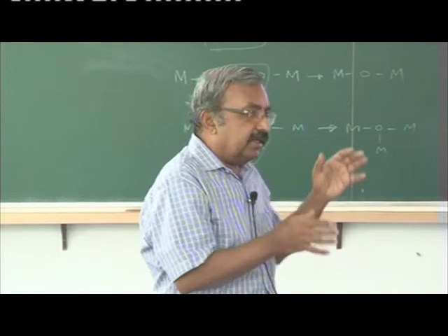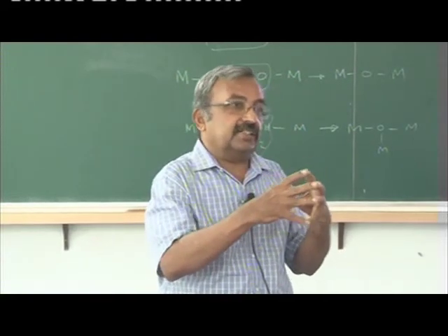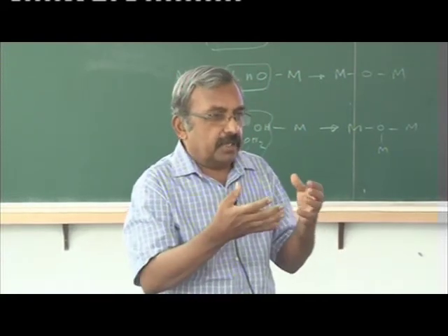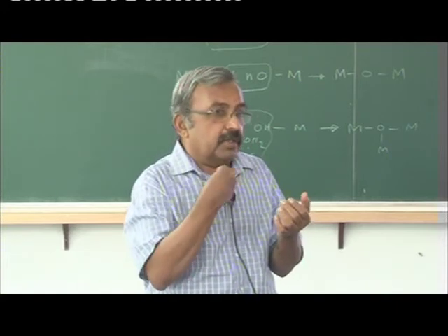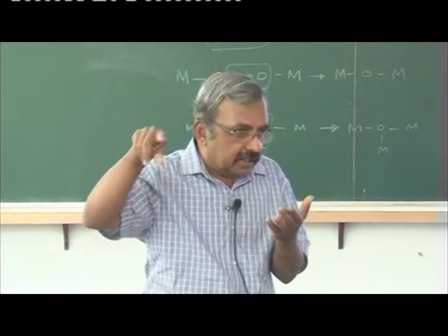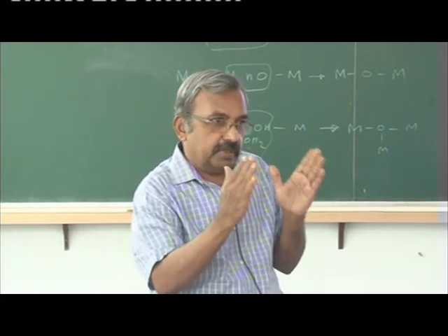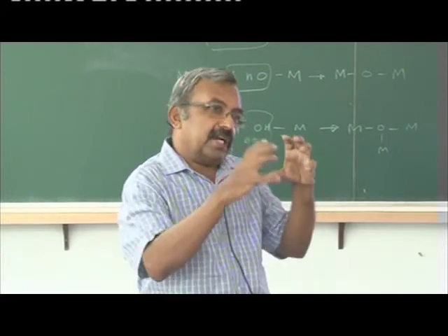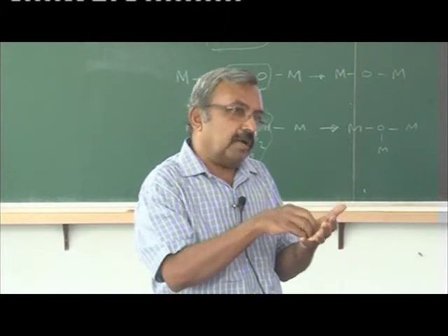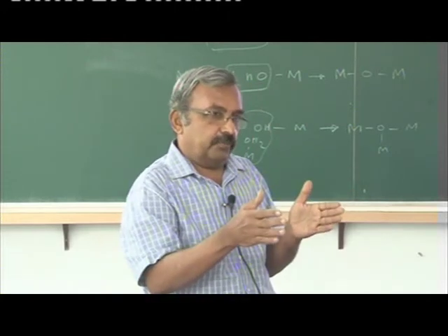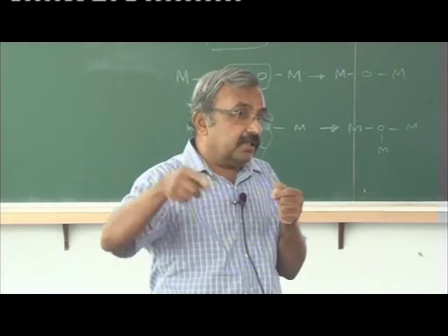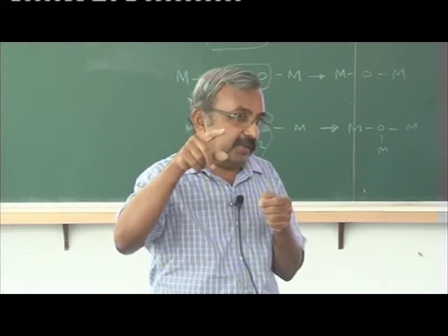You know that in particular cases, the Anderson clusters are stable. For example, the reason why we took chromium is because chromium will not interact with the ligand, and chromium is reasonably stable over the pH window we were using. So Anderson cluster chromium is a predominant species in that range. So we were only varying the metal ions and the complex.